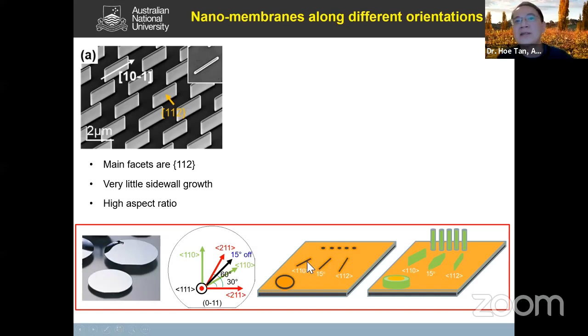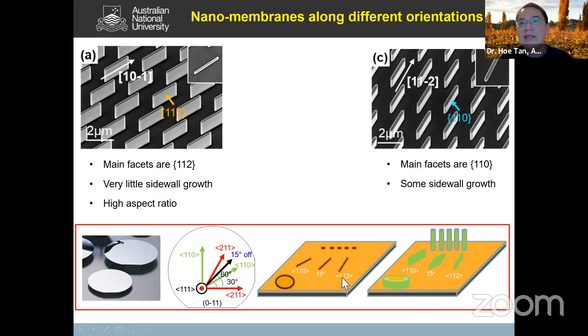on the indium phosphide substrate, and we grow, you can see we form this nanomembrane, which has a very thin sidewall. The length of the membrane is just defined by the length of the opening that you have, and the height is essentially determined by the time. So we get a very thin membrane. If we align it in the 112 direction here, it also forms a nanomembrane, but you can see it's much fatter. The reason for that is because the side facet here is 110, whereas in this case, the side facet is 112. Basically the growth on the 112 surface is much slower than the growth on the 110. That's why you end up with a self-limited growth. We have a very thin membrane.